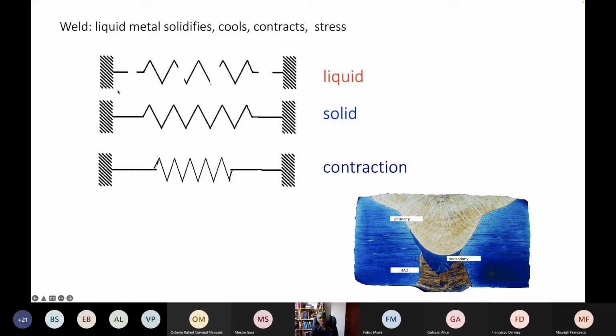So that's illustrated over here. Liquid can of course flow, so there is zero stress when this weld pool is liquid. As soon as it solidifies and the temperature drops, it will start contraction, and therefore you will build up a residual stress. And residual stresses can be very bad for the component in several different ways. So if there are any stress concentrations, they induce fatigue failure because the applied stress will be complemented by the residual stress. It also means that the stress that you apply to the component has to be smaller than you would expect from the yield strength of the material used to make the component.